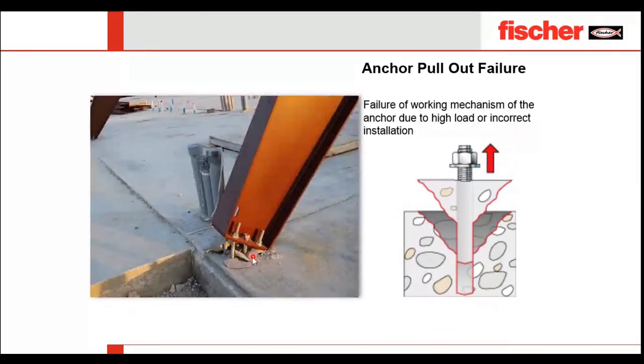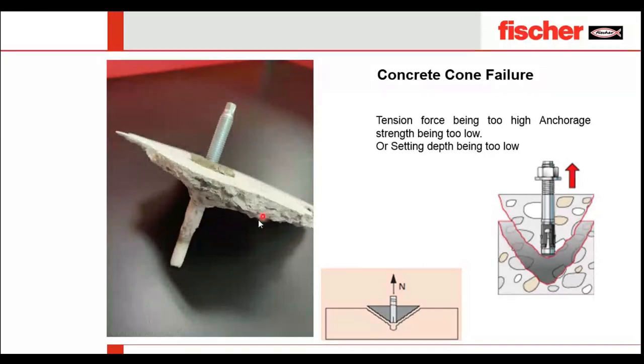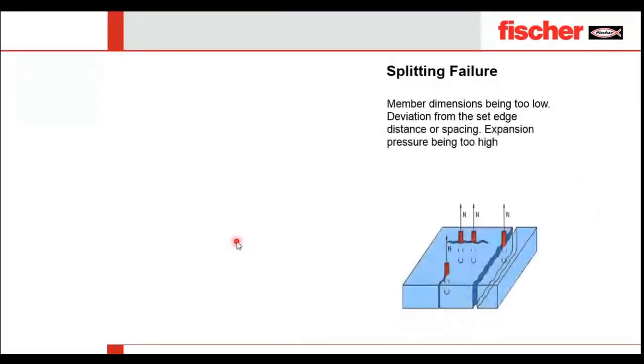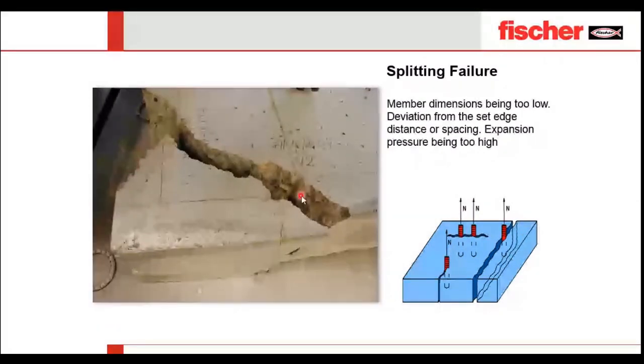When you have a tension force too high, or the anchor embedment depth is too low, or the setting depth is too low — where you don't have enough embedment depth — you can find this type of failure. For example, you can see a concrete cone failure that has occurred. Last is splitting failure: when the anchor dimensions are too closely spaced or when anchors are spaced too close to the edges, you can find similar failures.